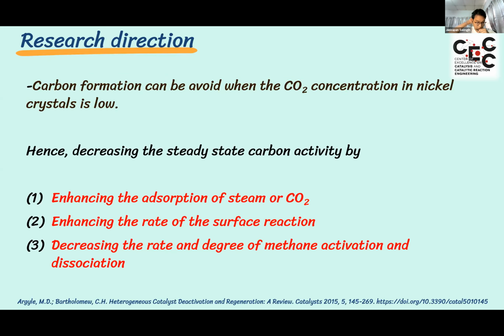And it is the last part about research direction. Carbon formation can be avoided when the CO2 concentration in the nickel crystal is lower than that at equilibrium, so we can decrease the steady-state carbon activity. First is by enhancing the adsorption of steam or CO2. Second is by enhancing the rate of the surface reaction. And the third is decreasing the rate of methane activation and dissociation.